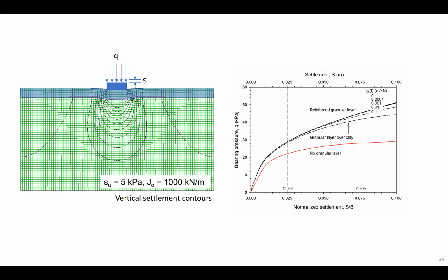So this slide is showing the effect of the curvature parameter. Here we've frozen J0 at 1,000, and we've just played around with the magnitude of that curvature parameter. And basically, as the material becomes less creepy, the curves move vertically up, which is not surprising. So a very creepy material has less capacity than a material which is closer to being inextensible, at least with time.